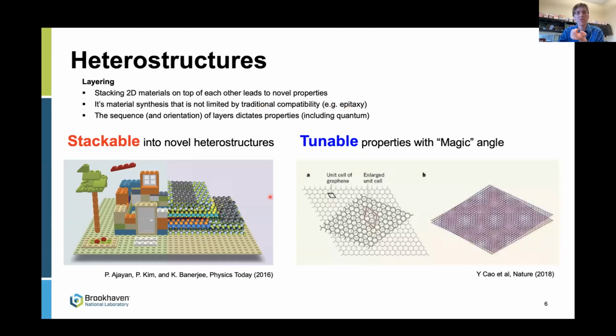But when you think about these 2D materials, you don't have that limitation. You can pick any 2D material and stack it on top of any other 2D material, and they can't stop you. The materials are just going to go on top of each other and form that stack. So you can get really, really complicated and arbitrary about what you choose to build. You're not limited by conventional chemistry. And as Shauna already alluded to, you can not just control the layer order, like what material goes on top of which other material, but each time you put down a layer, you can in principle choose the twist angle between them. And that twist angle can actually have a lot of interesting properties.